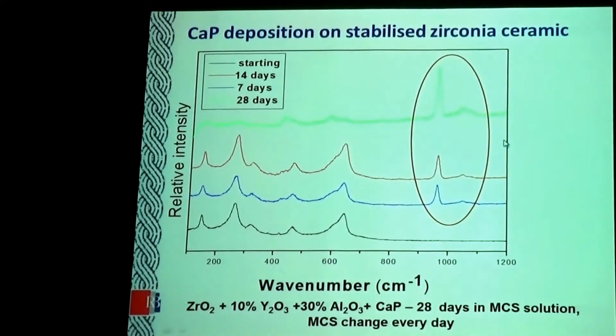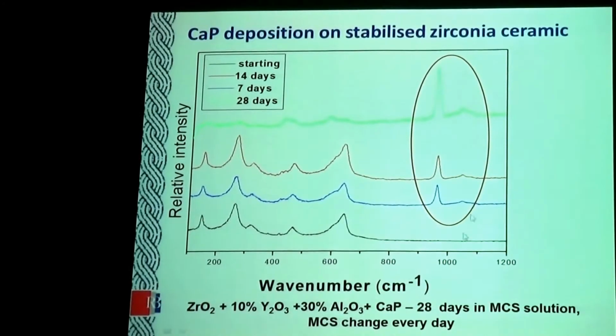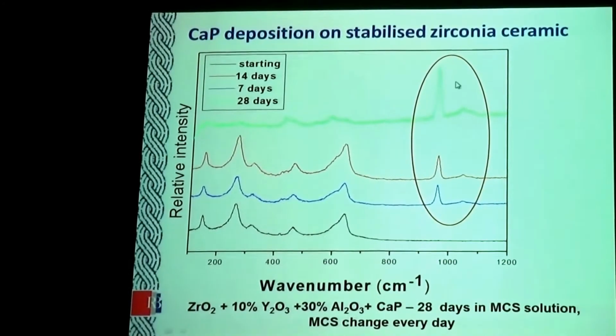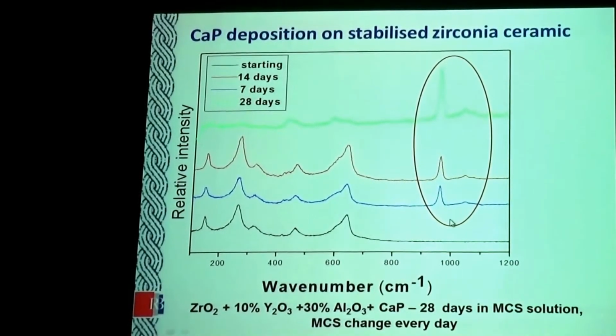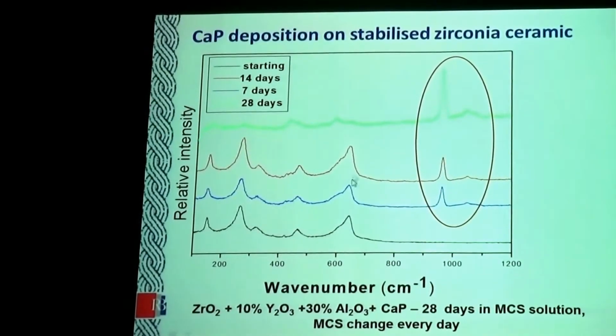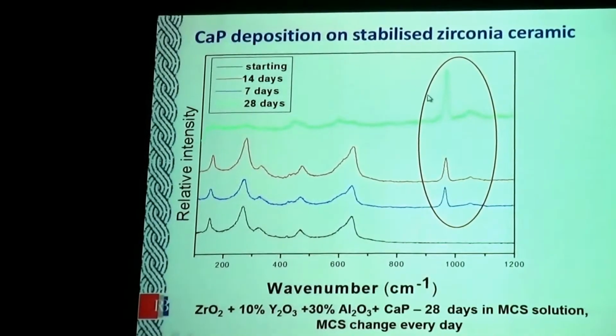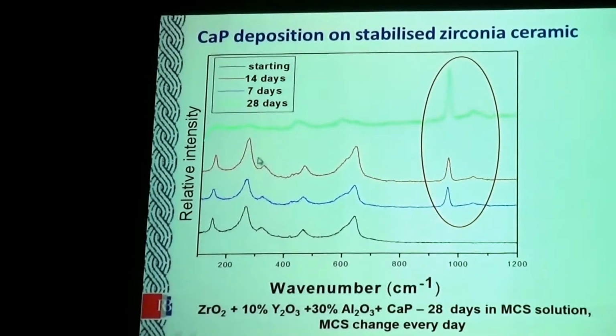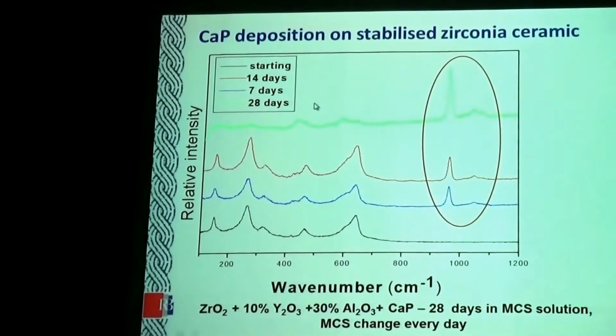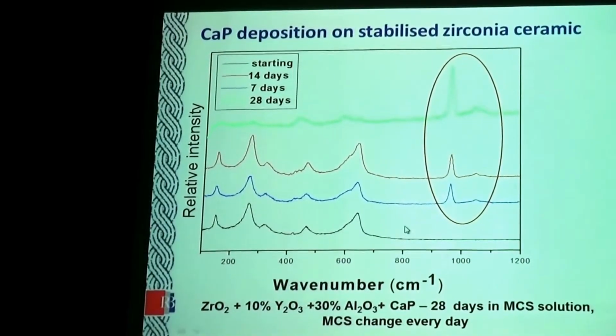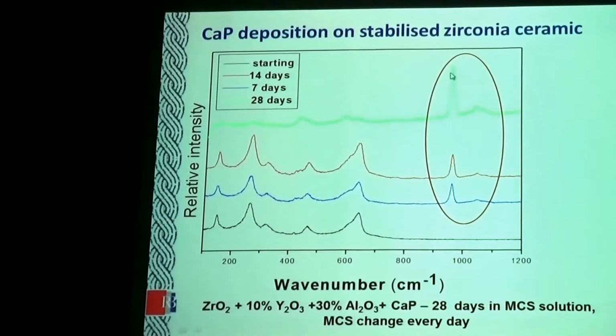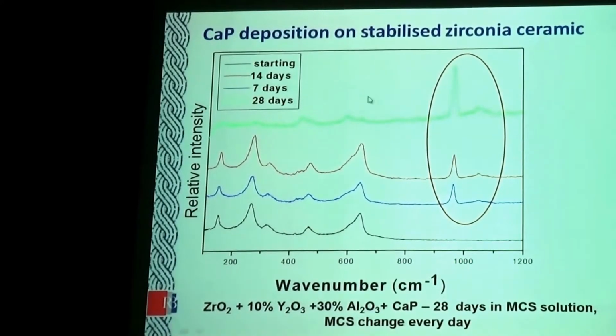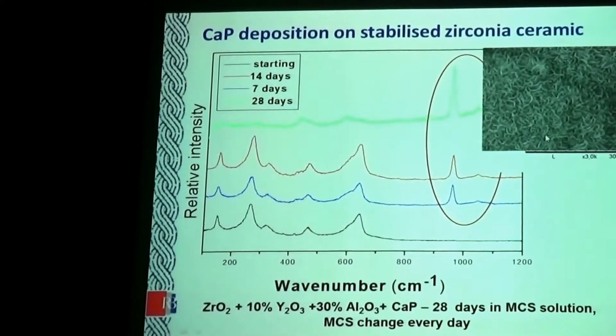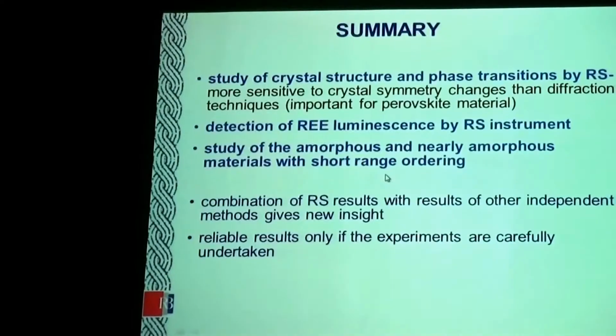This is the other study where we studied the deposition of calcium phosphate with ceramics. We compared the part of the spectrum belonging to calcium phosphates and the part belonging to ceramics, and with increased time in solution, we observed that after 28 days we have completely covered ceramics, completely covered with calcium phosphate.